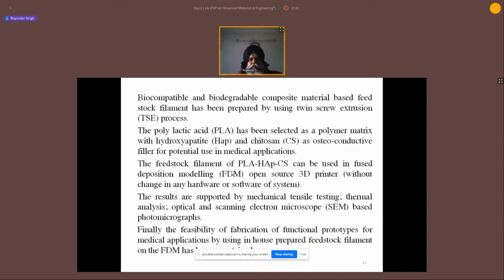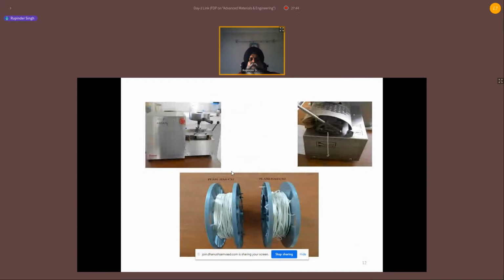So what we did is we used a typical twin screw extruder for this extrusion process. You can see this is the view of the twin screw extruder. I have intermeshing screws over here. I can put in different quantities of the load, I can use a different RPM, I can change the torque, I can change the temperature, and I can change the composition.